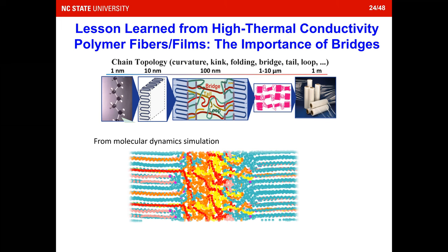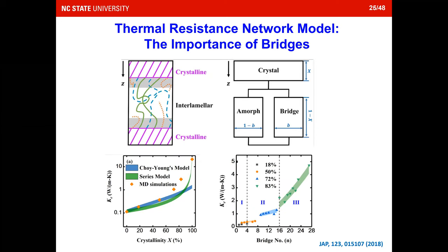They're connecting the two crystalline parts together, right? So it looks like there are just random chains, but they do connect those islands together. And then we're trying to come up with the same resistance network model and see whether our understanding is correct. Without considering those bridge chains, as described by the series model or Choy-Young's model, compared to our data, it does not describe it well, either at high crystallinity or in the median crystallinity. But with considering all these bridges, you can actually match the model data quite well.